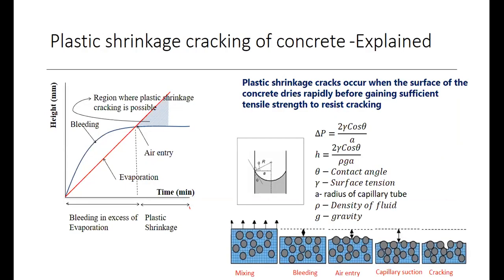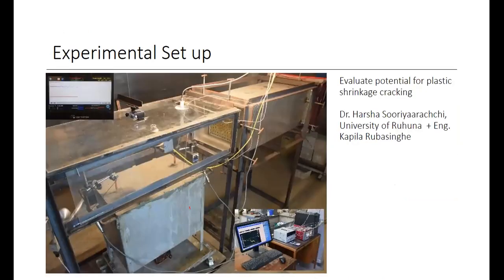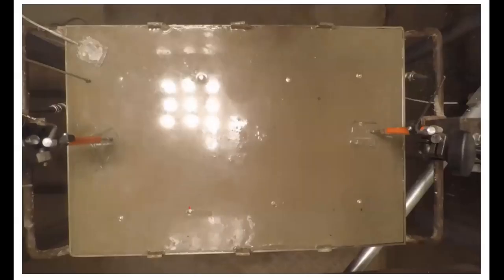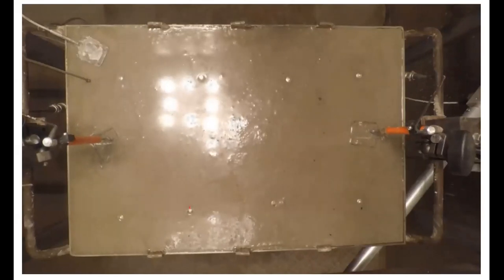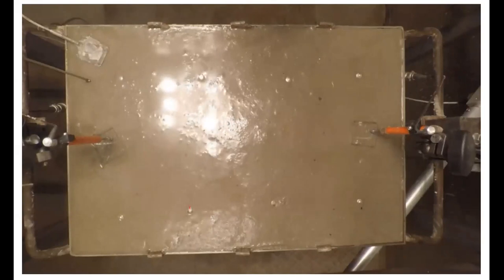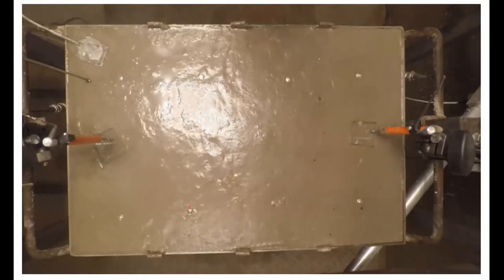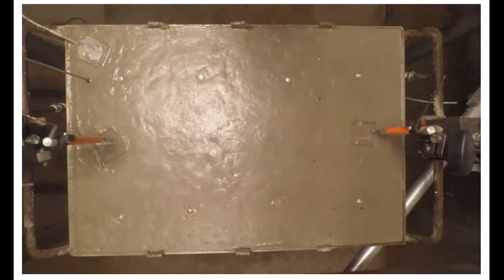For that particular matter, a lot of studies were done. Basically, Dr. Suraj has done a very good comprehensive analysis to identify the mechanism of this plastic shrinkage forming. And this is one experimental setup to evaluate the potential of plastic shrinkage cracking under different environmental conditions. You can see, this is a normal concrete. Actually, this video is short. The length of the video is 3 hours, but it was shortened. It was fast forwarded, so that you can see the reaction.